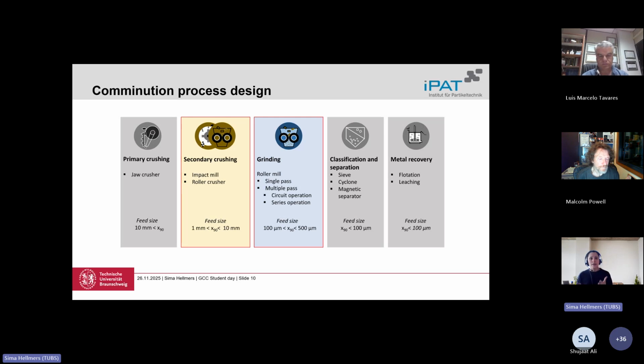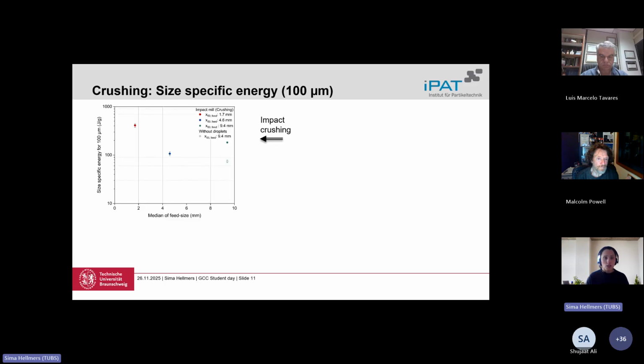So at the end, it could be suggested that there is a circuit for the fine grinding, because we need to grind and grind and grind to achieve our target size. Of course, we can put different classification methods and increase our recovery. My focus here would be on the secondary crushing and grinding. So we had 2 crushers. One of them was an impact crusher and the other one was a roller crusher.